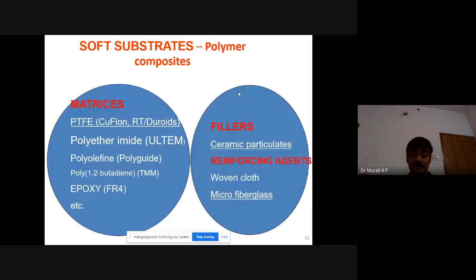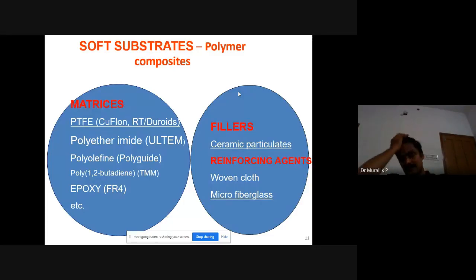And the fillers are mainly the deciding factor for how the electrical property has to be tuned. That will depend purely on the ceramic particulates. With ceramics, as you know, the dielectric properties can vary from very low, like 3.7 for silica, which I think is the lowest, to very high dielectric constants like TiO2, rutile, which gives nearly 100 or even more, strontium titanate, and similar ceramic materials which give a very high dielectric constant.